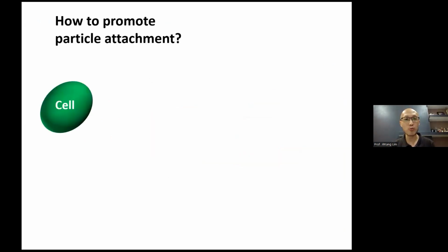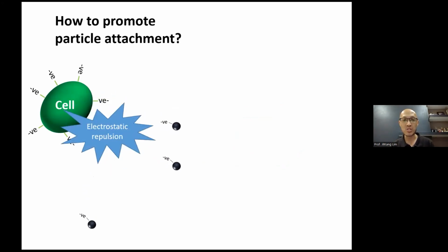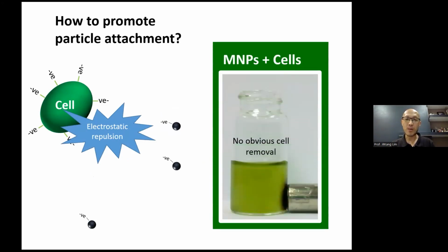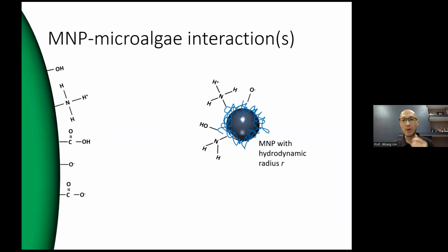Of course, the first question is how to promote such particle attachment. Because the microalgae cell is mostly negatively charged. And the magnetic particles we want to use, which are safe and can be used for environmental engineering applications, are mostly iron oxide nanoparticles, and iron oxide nanoparticles are also negatively charged. So if you just mix them together, they experience electrostatic repulsion, and the particles are not going to attach. If you mix the particles with the microalgae and try to separate them, the microalgae cells remain in the water, and whatever you add has no impact on the separation, since the whole interaction is driven by electrostatic repulsion.